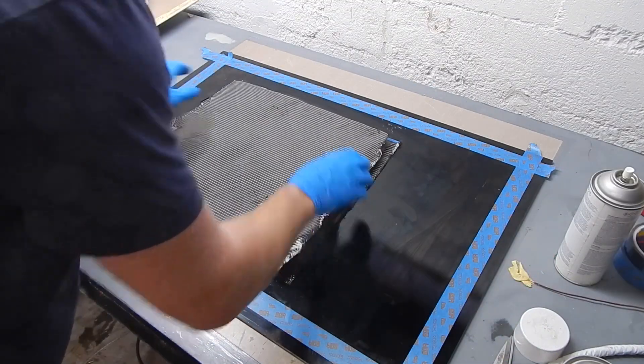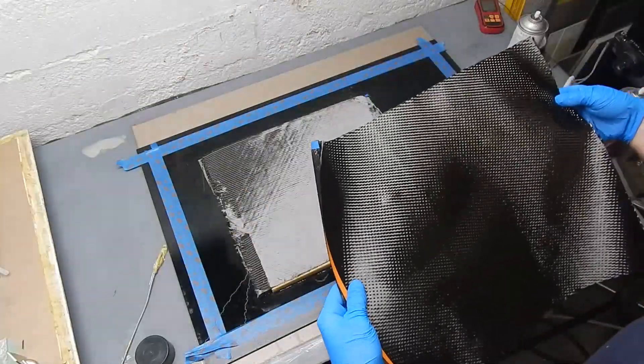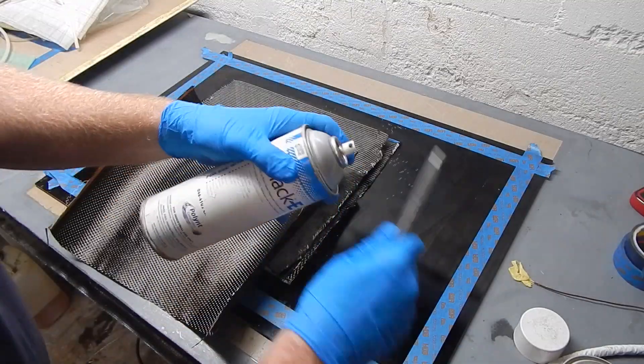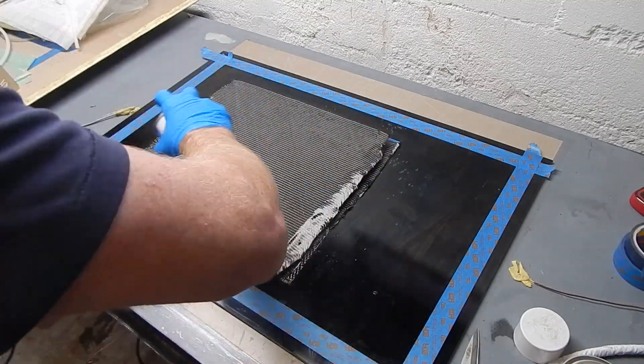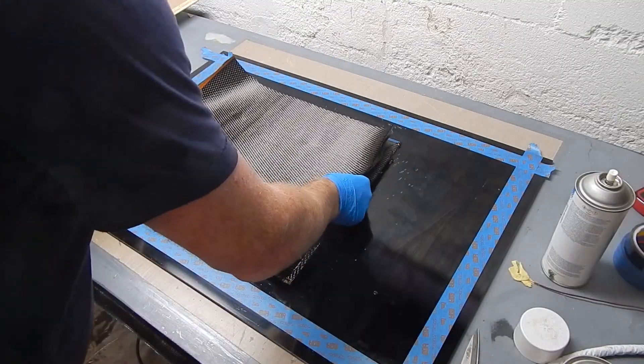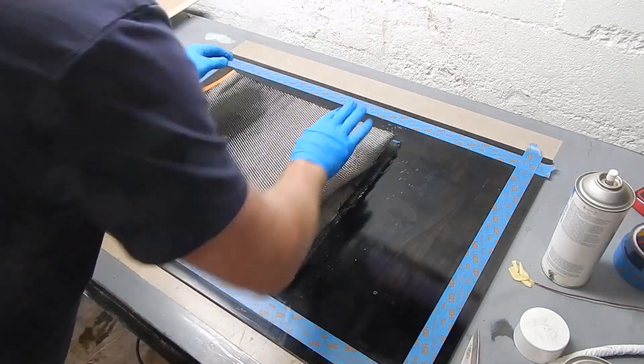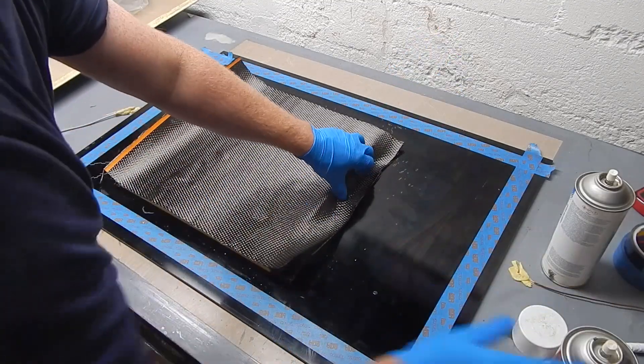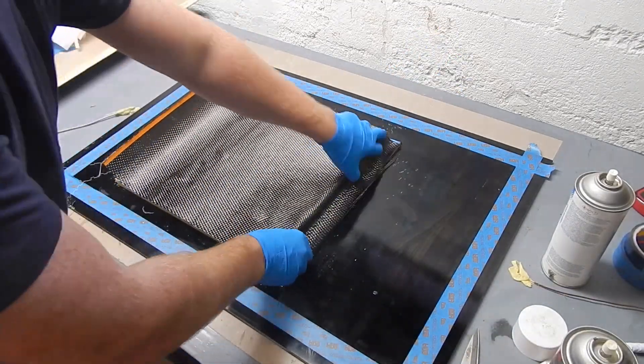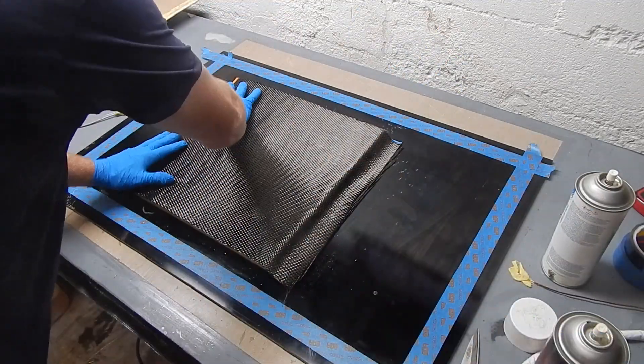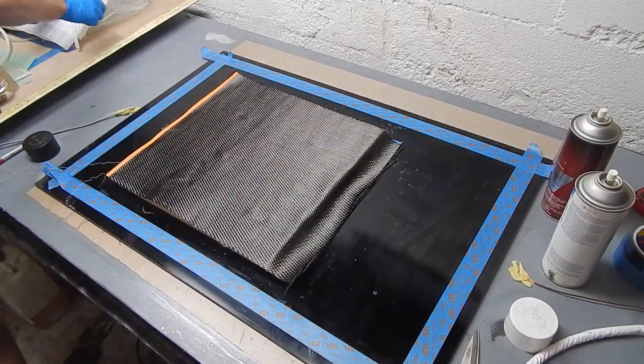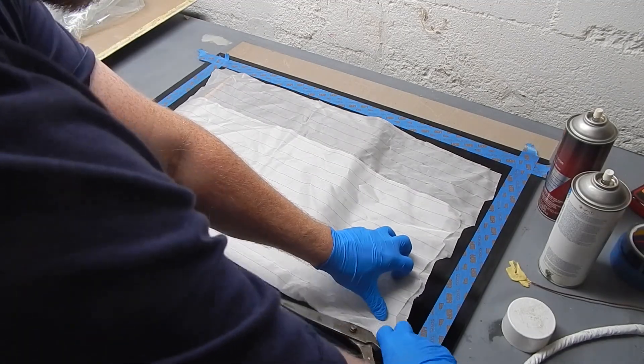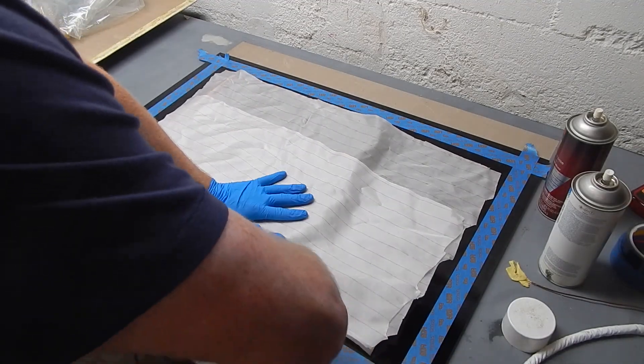I'm trying to de-gum that spray adhesive. There are a lot of different varieties of spray adhesive, good for different things. Many resin soluble, many not. This 3M Super 77 is sort of the basic. You want to use very little of it, but it does work, and it's easy to get. But it is not resin soluble, so it leaves a contaminant in the finished part.